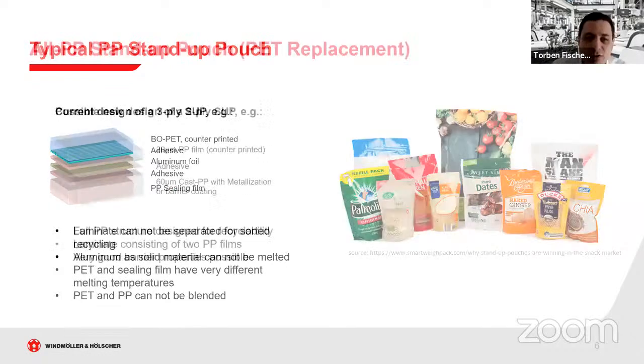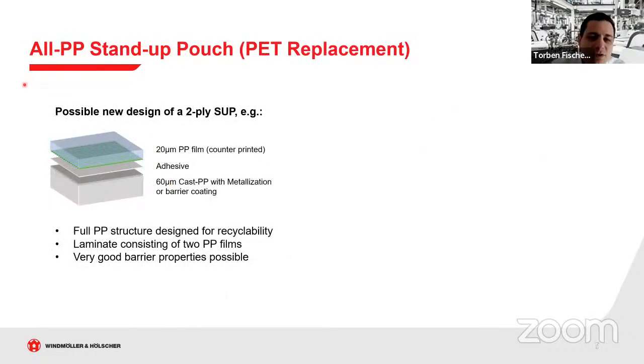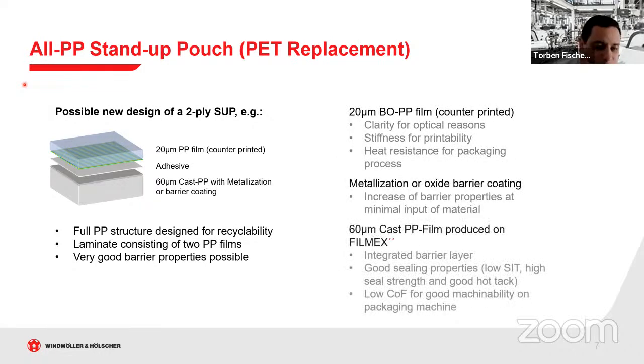And one of the solutions we can come up with is to replace the PET with a PP film and create a different functionality when it comes to improving the shelf life. This is one of the solutions we came up with in recent years. So this new setup is only a 2-ply pouch. It consists of a BOPP film, which is counterprinted for the labels, and underneath, we have a 60 micron cast film. And this cast film has been metallized by special processes to give us the barrier properties.